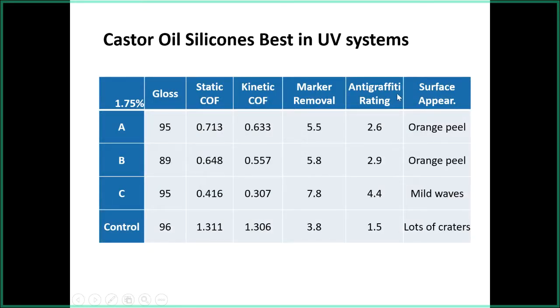And just a quick sense of the data. Here we've got some properties across the top. 1.75% of the castor oil derivatives were added to a coating system. It's a UV cured system, with 3 different castor oil derivatives and the control at the bottom. There was a minimal impact on gloss, and coefficient of friction went down to a quite reasonable 0.4 and 0.3 numbers.